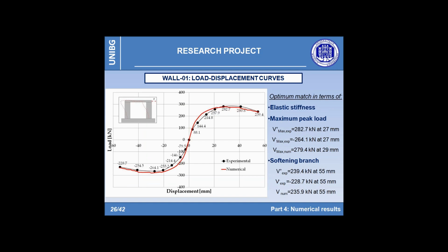These figures show first how for wall 1 the numerical result exhibits a good match in terms of elastic stiffness. The model seems to be also able to correctly catch the peak load, in particular 282 kN and 264 kN for the experimental test and 279 for the numerical one.